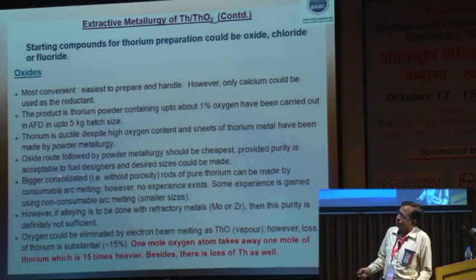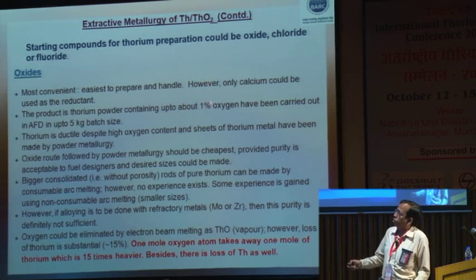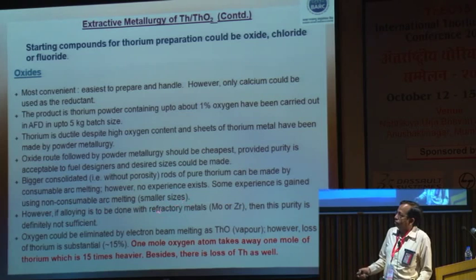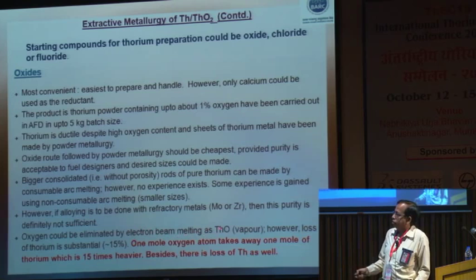If you want to alloy this thorium, you don't want this 1% oxygen. So we have to have much purer metal for making alloys with moly or zirconium. And the problem is of reducing this oxygen. One way is electron beam melting to remove this oxygen, but along with this oxygen, thorium will also go away, and you'll start losing about 15% of thorium. So this is not a very attractive method for having an oxygen-free product.